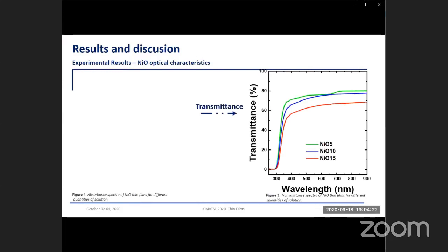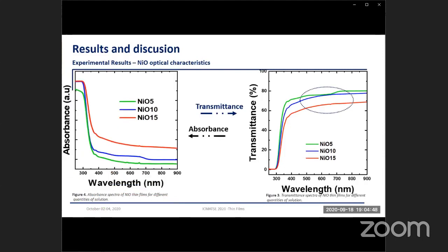In our study, we are focusing on the optical characterization. Nickel oxide shows high transmittance in the visible range, reaching 79%. Nickel oxide 5 and nickel oxide 10 do not show a big difference, while nickel oxide 15 shows a drop of transmittance, decreasing by 18% compared with nickel oxide 5 and nickel oxide 10 films. The absorption of nickel oxide films decreases as wavelength increases. In other words, nickel oxide shows high absorption in the UV range, and the absorption increases with the increase in the quantity of solution.